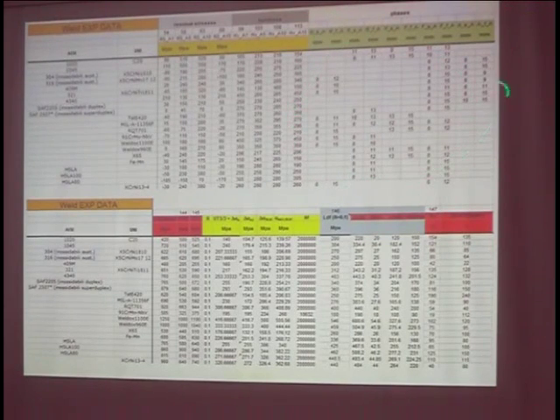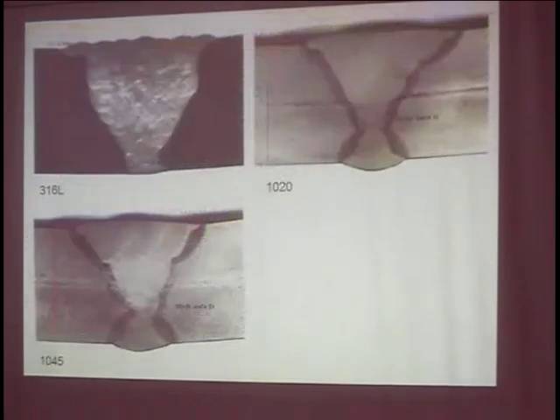And here we checked the microstructure in terms of martensite start and finish formation, bainite, perlite, ferrite, and austenite, taking into account the same point in which micro-hardness and residual stress were measured. In this way, we are able to check point by point the evolution of microstructure and mechanical properties of our welds. And here we measured the tensile properties, fatigue, and impact strength with respect to the base metal resistance in this case.